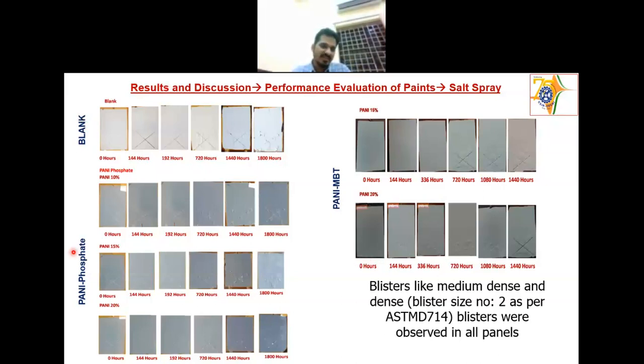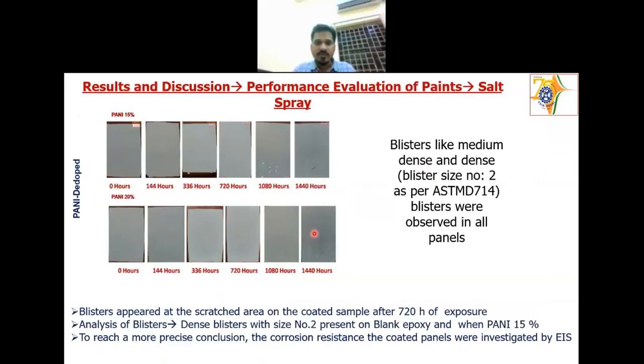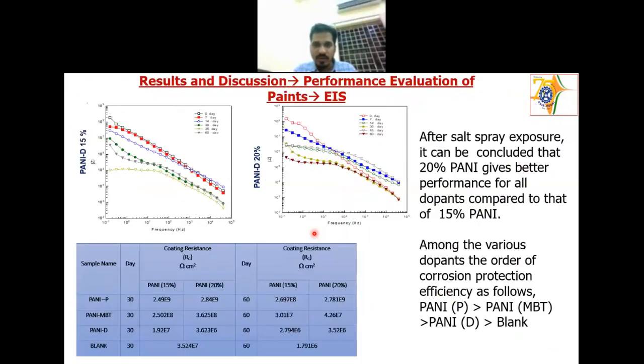A blank coating, and this is the Pani phosphate and Pani MBT. We actually developed various other formulations also, using various benzoates, Pani benzoate or Pani quinoline and Pani hydroxyquinoline. We used various things, but here we are showing only three right now. After almost 2 months, 1440 hours inside the salt spray chamber, we found that more blisters were there in the blank coating, but when the Pani was there, the blisters were fewer. And then the most important thing is whether the coating can act as self-healing or not. So I will go into that in another slide.